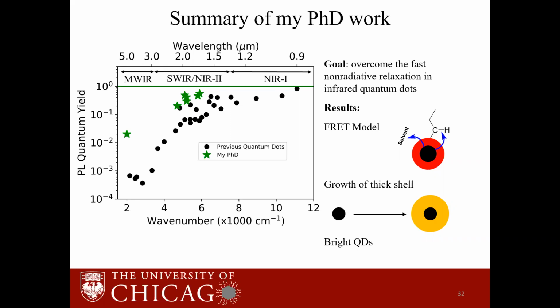So this trend is because the ligands are strongly absorbing at this region, and by growing this shell, we are separating the core from the ligands, and we are slowing that relaxation rate. To go brighter, either you need to grow a really thick shell, or you completely remove these absorbing ligands and put something else, like some inorganic ions or inorganic matrix, and that will slow the rate. But we need to find some way to slow the FRET. So it's not intrinsic to the quantum dot material, but intrinsic to the environment around it.